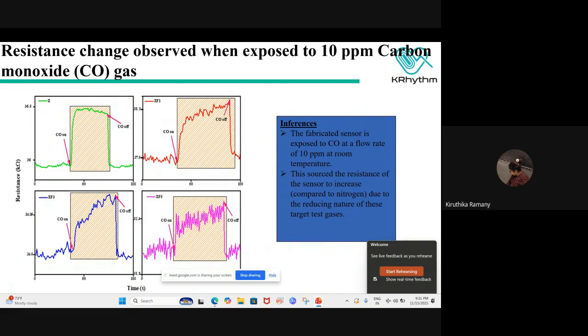So this is the resistance change that was observed when we exposed the sensor that we fabricated to 10 ppm of carbon monoxide gas. CO on is the reference, that is the baseline. The time taken for the sensor to attain its maximum resistance upon exposing to the target test gases is the response time. And the recovery time is the time taken for the sensor to revert back to its original or base resistance after turning off the target test gases. So CO off is the time that we have turned off the test gases. The resistance of the sensor came back to its original value.